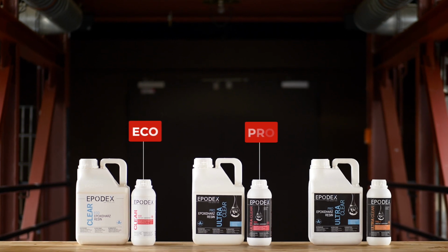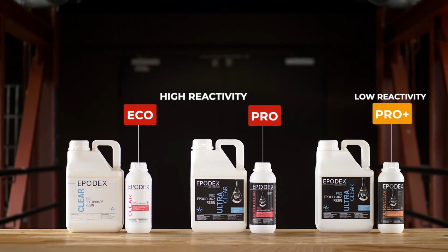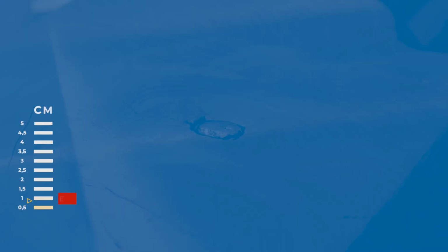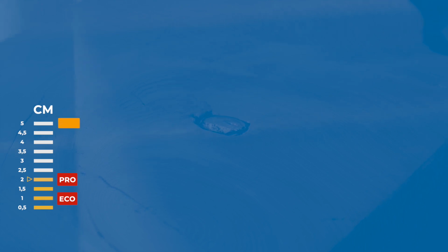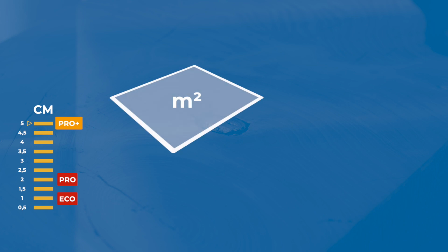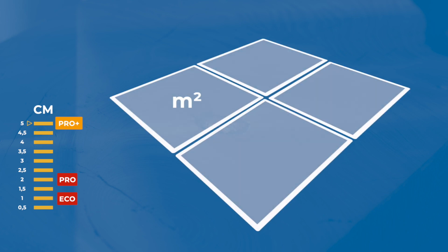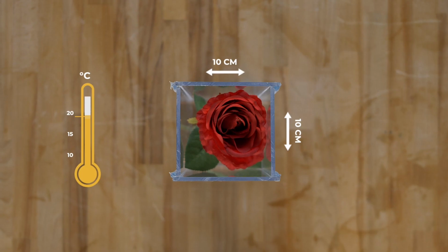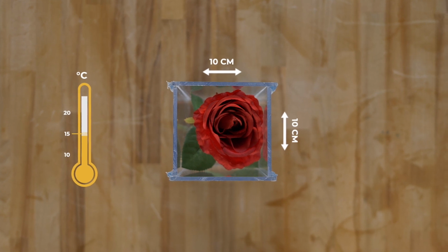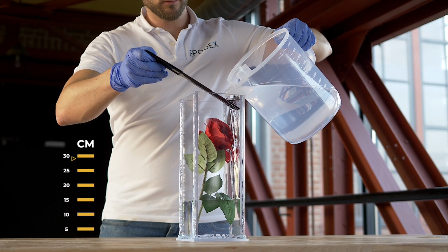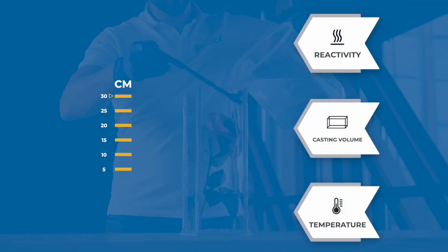EPODEX's Eco and Pro system are more reactive than the Pro Plus system. While you can pour up to 1 cm with the Eco system and 2 cm with the Pro system, the Pro Plus system can be poured up to 5 cm thick in one pour. For all three systems, the maximum thickness applies regardless of the size of your project, at room temperature of approximately 20 degrees Celsius. If you pour small areas or lower the room temperature, you can cast with our Pro Plus system up to 30 centimeters thick at once. The maximum pouring height is not only determined by the system's reactivity, but also by the area to pour and the temperature.